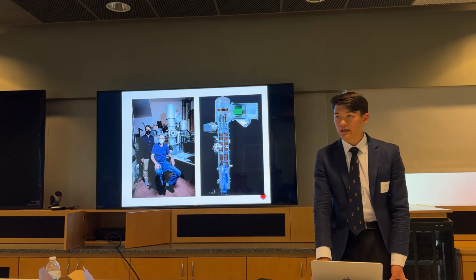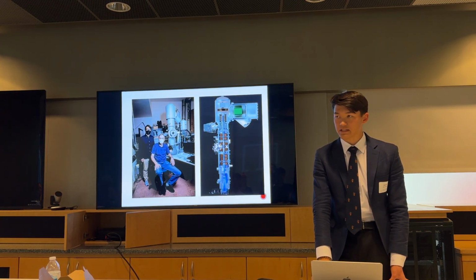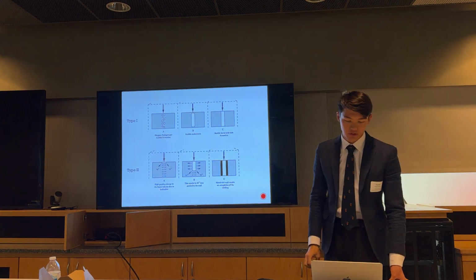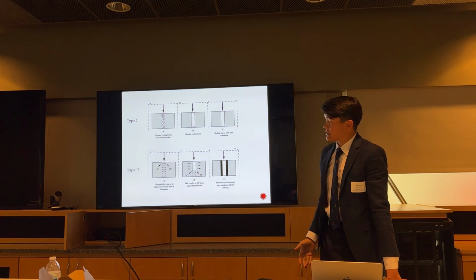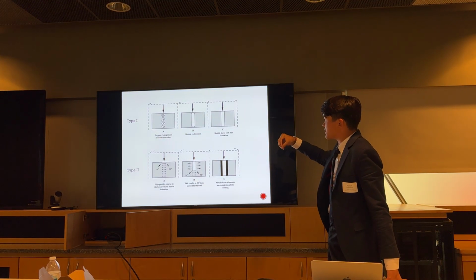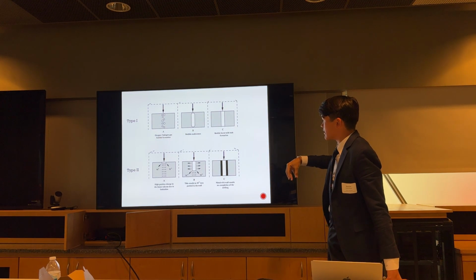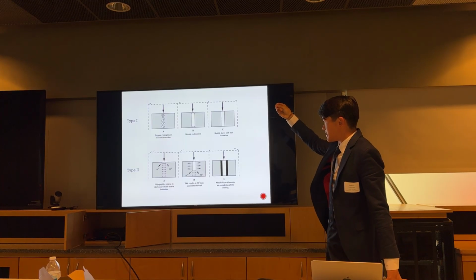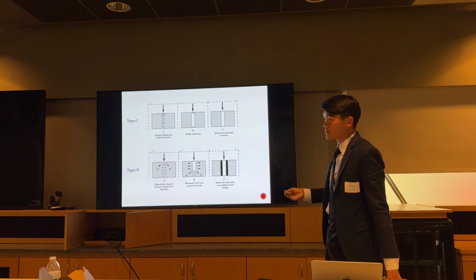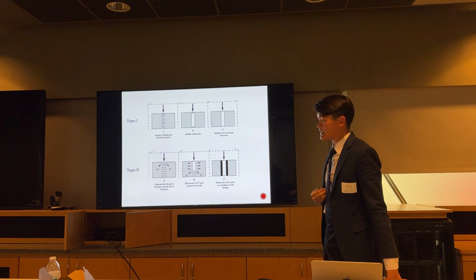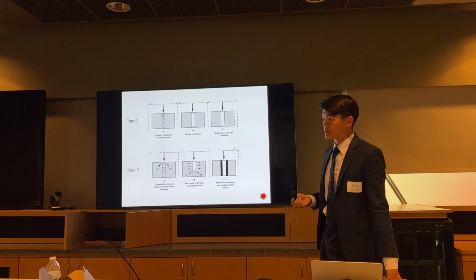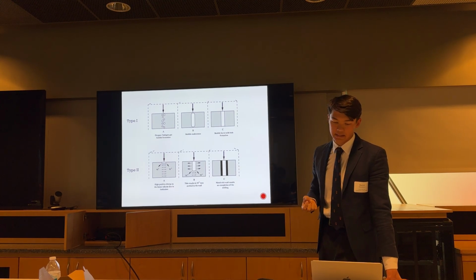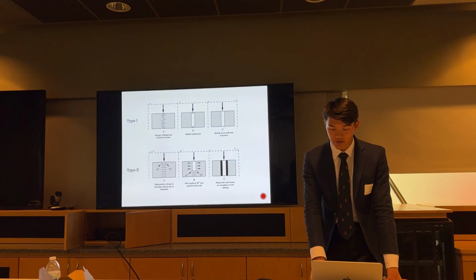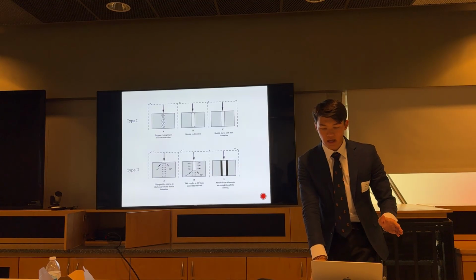The specific way in which ytterbium fluoride develops isn't fully understood yet, but here are two possible hypotheses. One is that bubbles form, which then coalesce and form a channel like this. Another is that the channel itself grows from the top to the bottom. We're still not certain which exact way it is, but we do know from experimentation that ytterbium fluoride does get developed by an electron beam. So we have that trench,